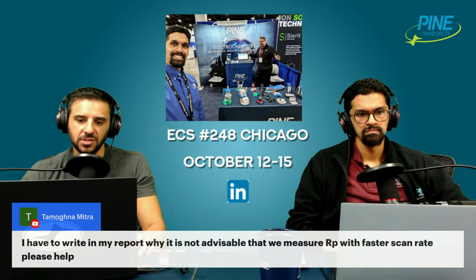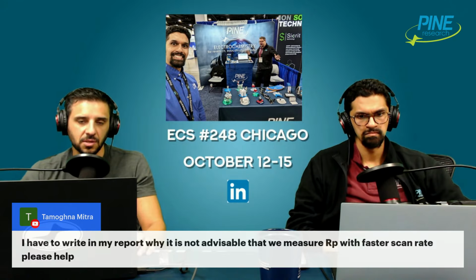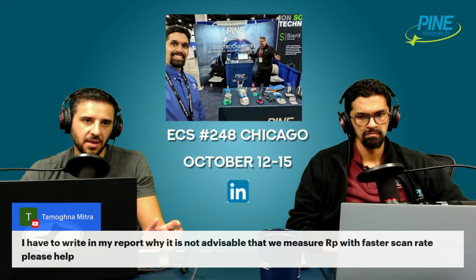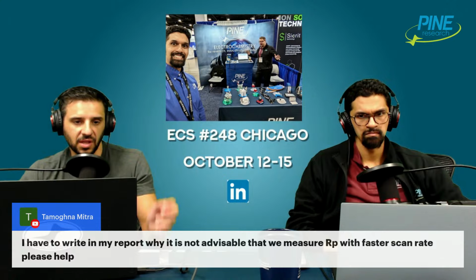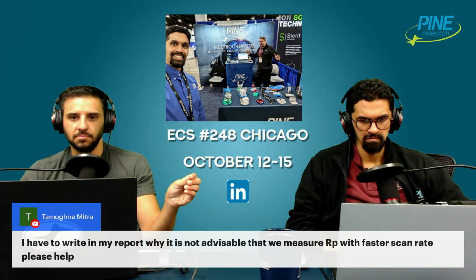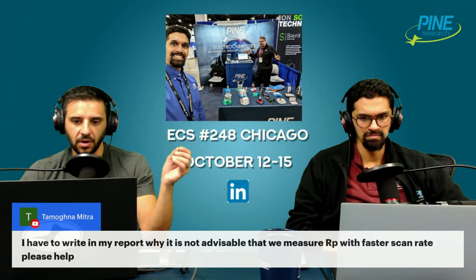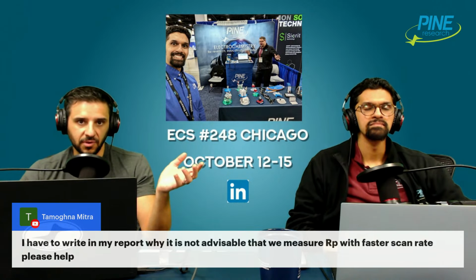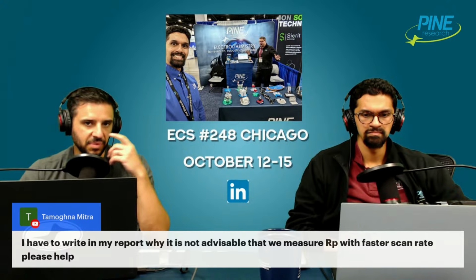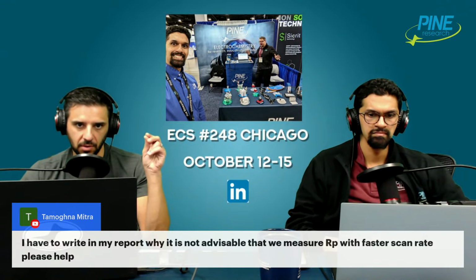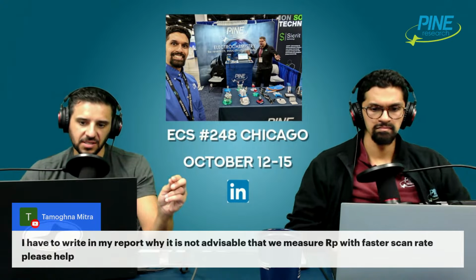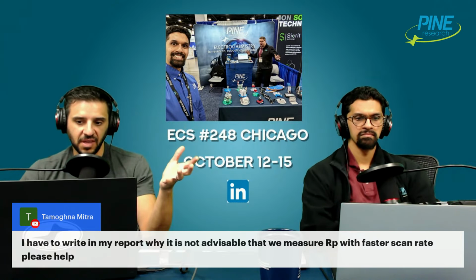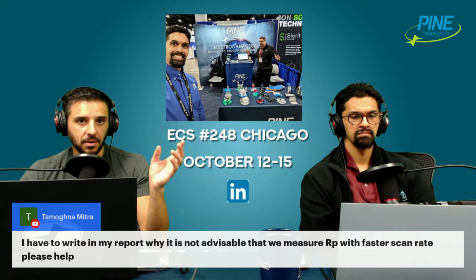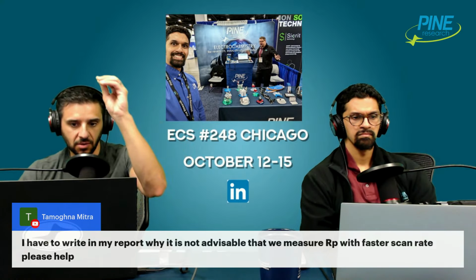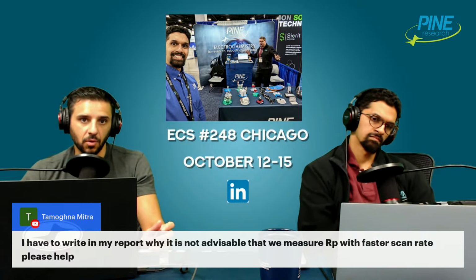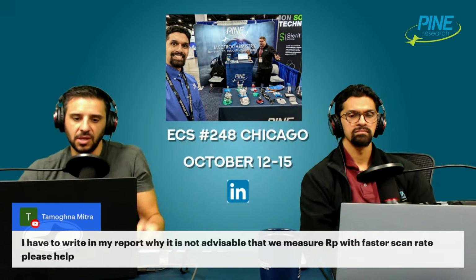You could even try doing a whole bunch of chronoamperometry measurements. So instead of sweeping from minus 10 to 10 millivolts or whatever, you could hold at minus 10 millivolts for a minute. That's excessive, maybe 30 seconds, whatever, right? And then pick an interval that's not going to make you crazy. You don't want to do 5 billion points, but let's just say every 1 millivolt. So hold at minus 10, hold at minus 9, hold at minus 8, and then you make your IV or VI plot with the steady state current at each of those chronoamperometries. That's another way to get the slope, and then you get another RP.